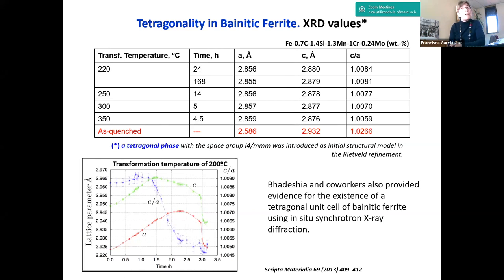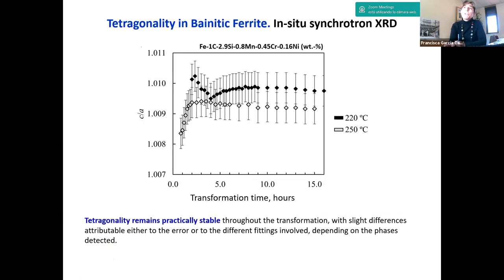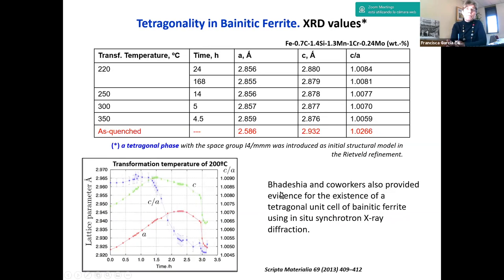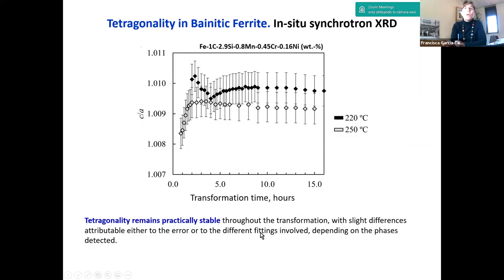That tetragonality, apart from X-ray analysis, was also measured by Bhadeshia and co-workers by synchrotron, and you can see the tetragonality at 200 degrees C as the transformation is taking place. We performed synchrotron experiments too. We studied two temperatures, and again we see that the tetragonality decreases with increasing transformation temperature. But looking at the previous experiments, 3.5 hours, here 15 hours, what we saw is that the tetragonality is quite persistent. It remains practically stable at the transformation temperature. This is really, really interesting.